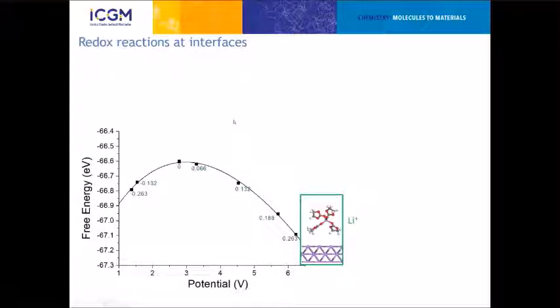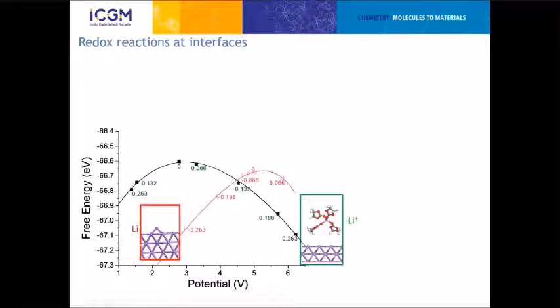So next, in my little tutorial, how do we model electrochemical reactions at an interface? In fact, we need a redox pair. We have some species that will react as the oxidant, for example, some kind of Li plus over the surface. And we will need another interface that will be the reduced interface, in this case, for example, lithium that will be deposited on the surface. And in this case, when we have computed that, we can extract the electrochemical reaction.